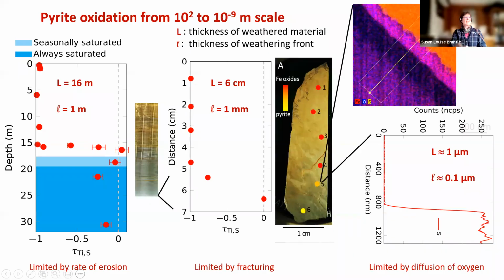So if we put this together across the whole scale, this is the first time in my career that I was able to do this. Here's the pyrite oxidation front shown at the borehole scale. I started out, so this is meters. And then at the sort of clast or fracture scale, here it is where it's sort of 6 centimeters inboard with a millimeter reaction front. And then here is that TEM scale that I was showing you, you know, how thin that front actually is at an atomic scale. So again, if we use that 50 kiloyear time constant, the rate has to be, these pyrite grains are 5 microns. So there's a 5 micron pyrite in 50 kiloyears.